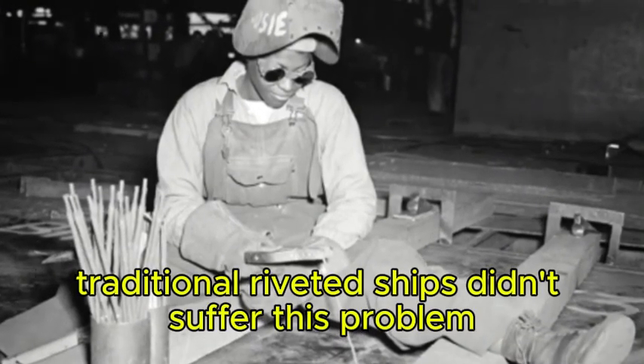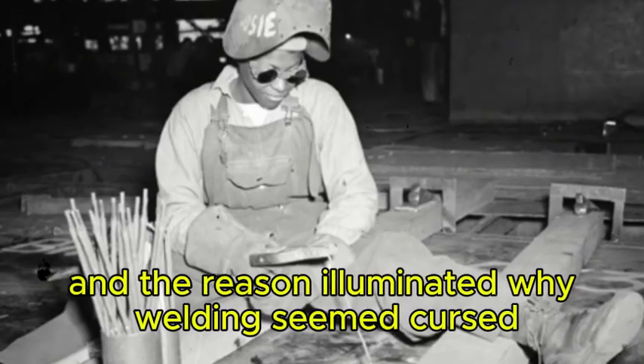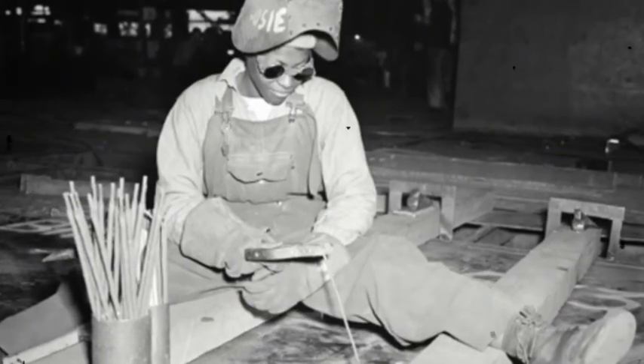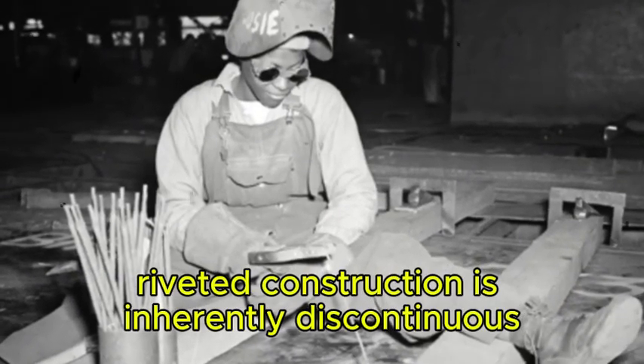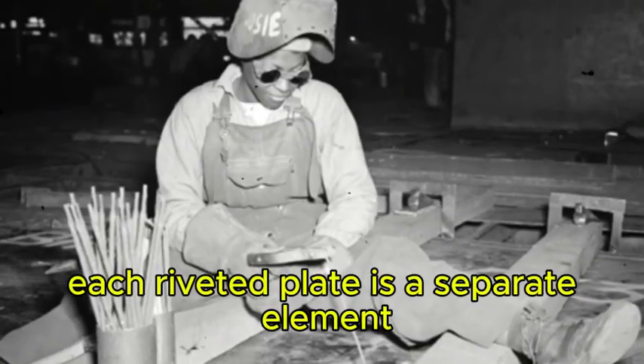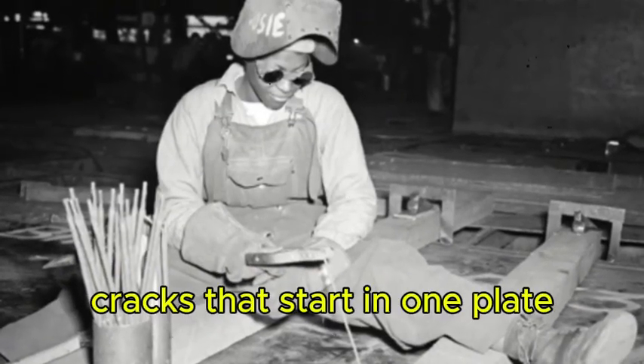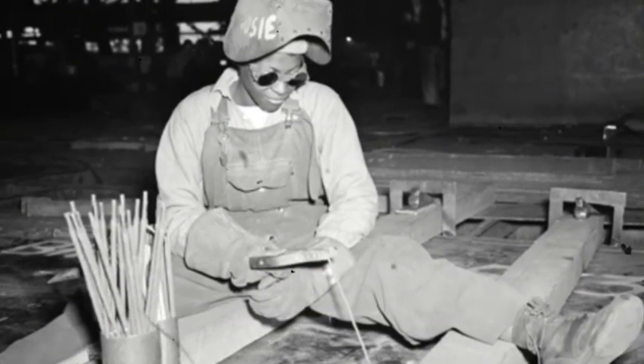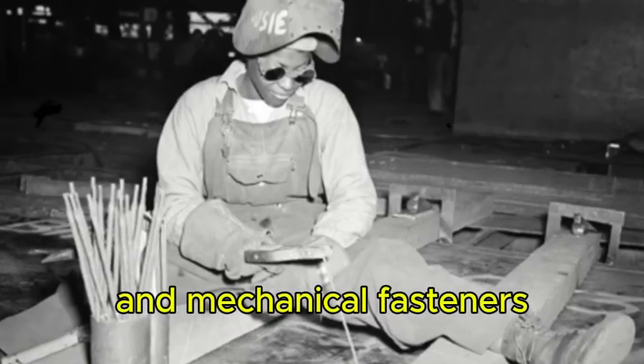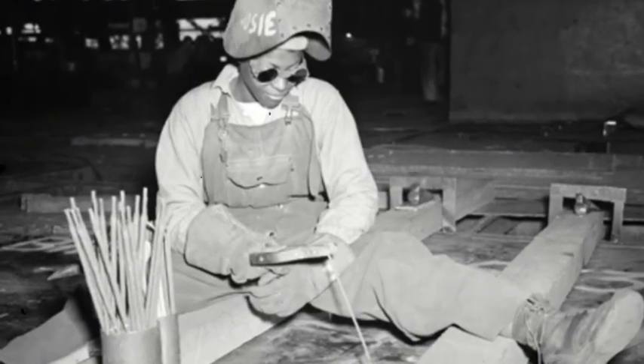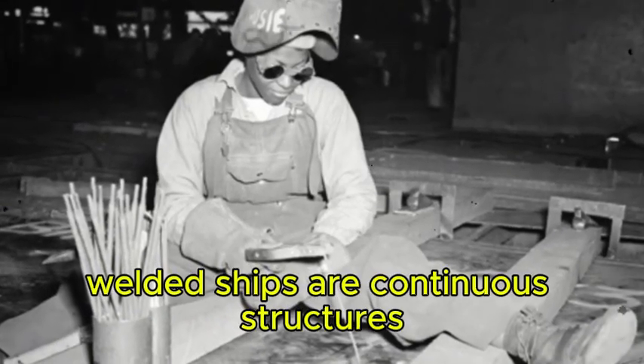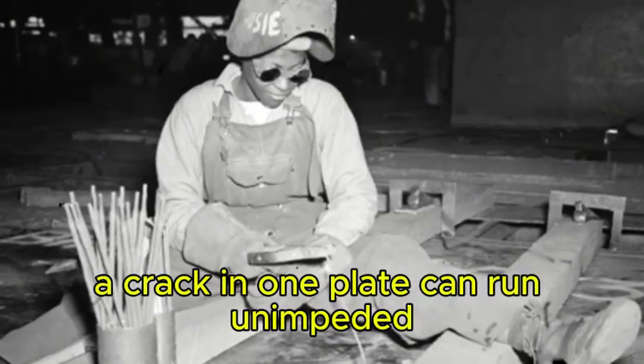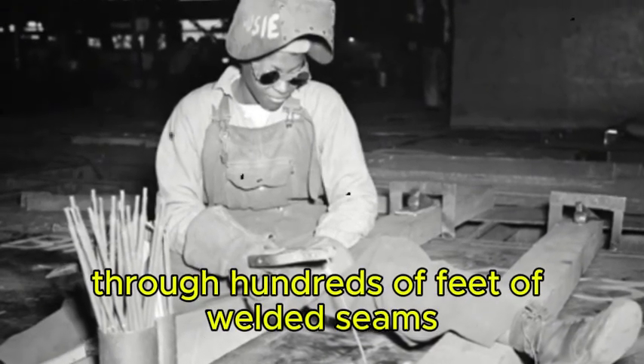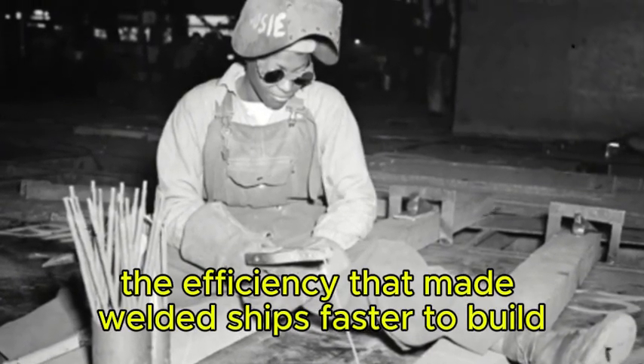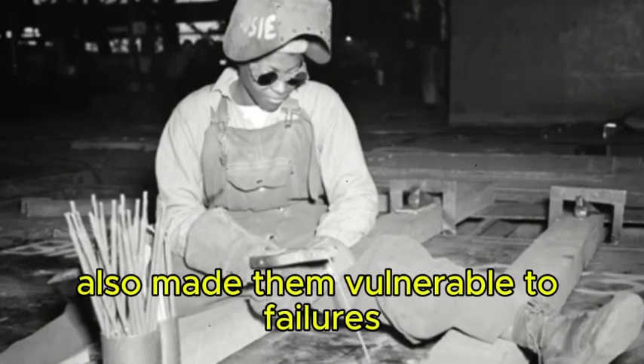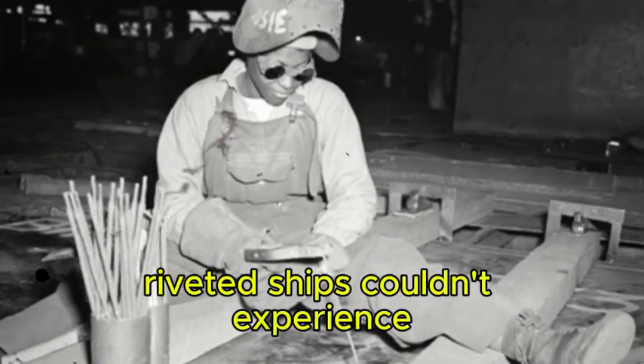Traditional riveted ships didn't suffer this problem, and the reason illuminated why welding seemed cursed. Riveted construction is inherently discontinuous. Each riveted plate is a separate element. Cracks that start in one plate hit a riveted seam and stop. The overlapping plates and mechanical fasteners create natural crack arresters. Welded ships are continuous structures. A crack in one plate can run unimpeded through hundreds of feet of welded seams. The efficiency that made welded ships faster to build also made them vulnerable to failures riveted ships couldn't experience.